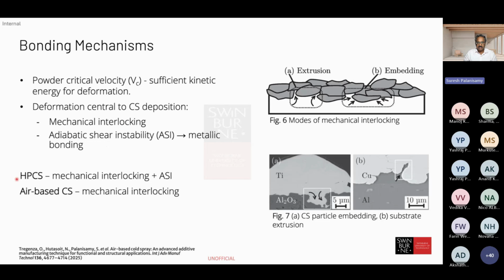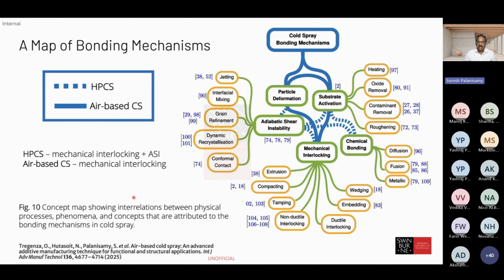Mechanical interlocking happens, and adiabatic shear instability is one of the main modes of the bonding mechanism, along with metallic bonding. With high pressure cold spray, mechanical interlocking with adiabatic shear instability makes it a stronger, better bonding mechanism. In air-based cold spray systems, mostly mechanical interlocking happens. So quite a number of different modes of bonding mechanisms are there, depending on which application and which method you are using. As you can see, the dotted lines and solid lines show different parameters and conditions. With jetting, material interface, and grain refinement, quite a lot of mechanical interlocking and structural changes can also happen. This is just a concept map.